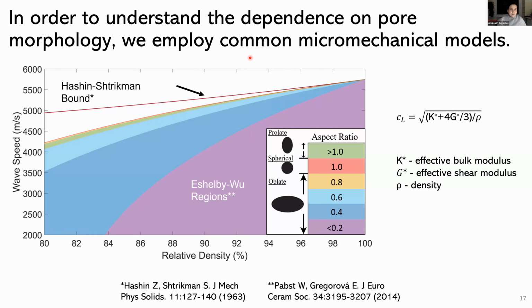So we knew for a fact that there was going to be porosity. We had relative density measurements that reflected that. But what we did not know was whether those pores were fairly spherical and uniform in shape, or if they had some preferential shape that we were perhaps capturing with some of our ultrasonic results. So what you see in this figure is the Hashin-Shtrikman bound, so the upper bound for that wave speed and what would fall there. And then what you see in the colored bands is that we actually look at the HS regions based on different aspect ratios for the pores.